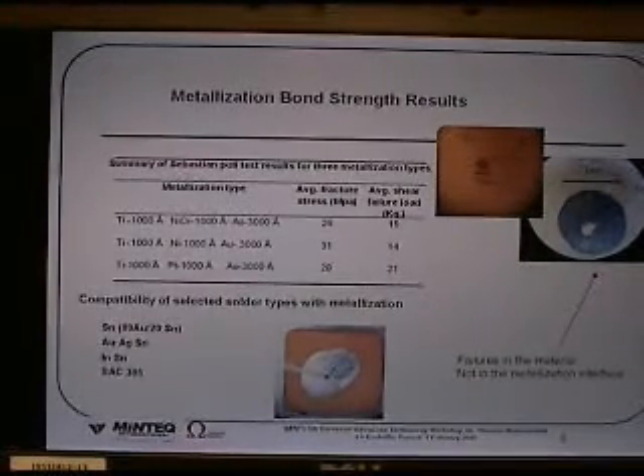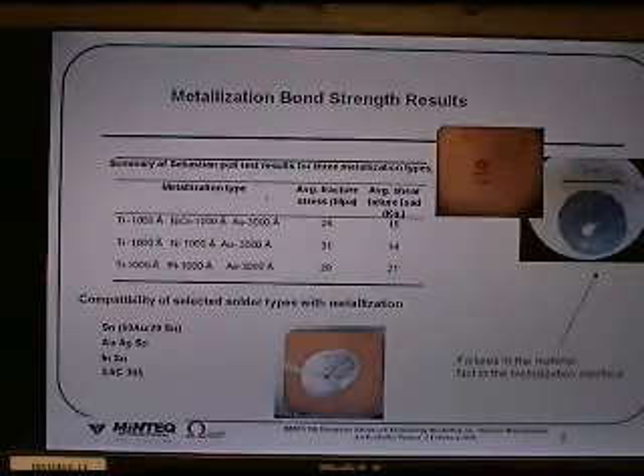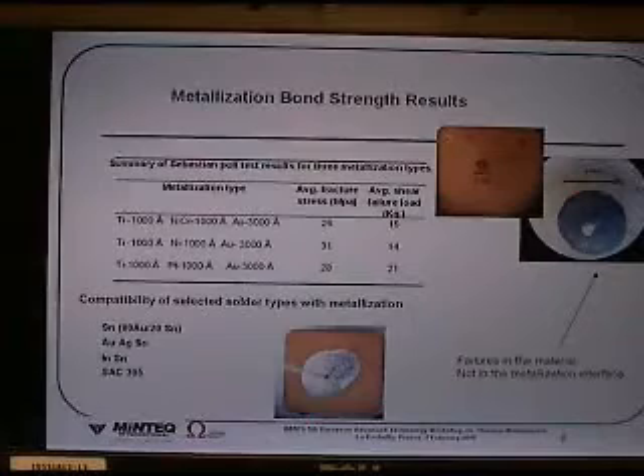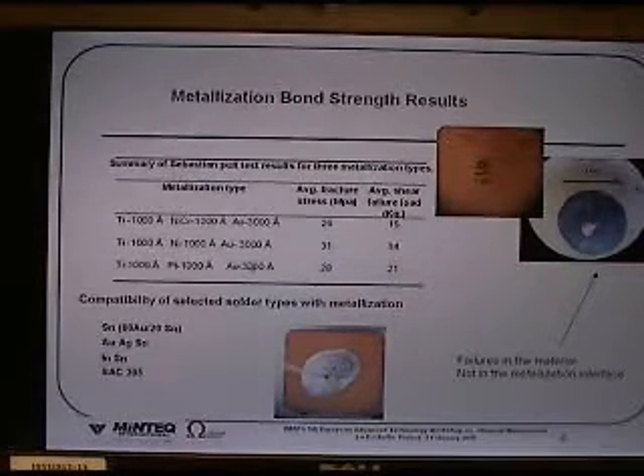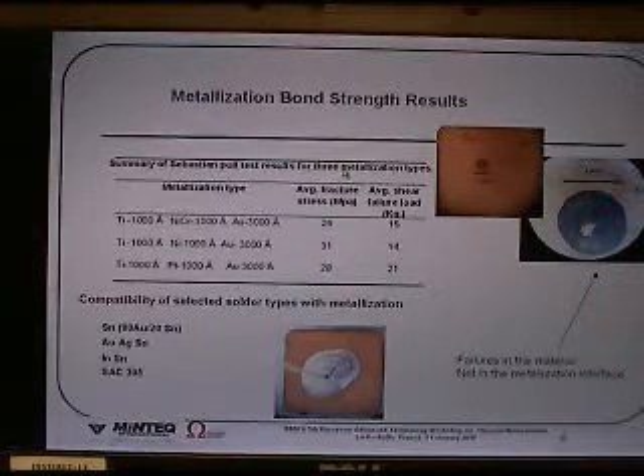Metallization development was very important to ensure that we have an acceptable bond strength. The work that we've done has been verified by an outside testing laboratory which has conducted Sebastian pull tests, a common test that allows us to test various metallization schemes using MIL-STD-883. The results of that metallization bond strength testing verify for us that we can use a wide range of metallization schemes: a titanium first layer that allows for strong adherence to the pyrolytic graphite, a barrier layer, which could be either nickel or platinum or nickel chrome, and finally a gold layer, which allows for extremely good adherence to electronic devices. We were able to offer both an acceptable fracture stress and shear failure load that would make this material readily acceptable for a wide variety of electronic uses.